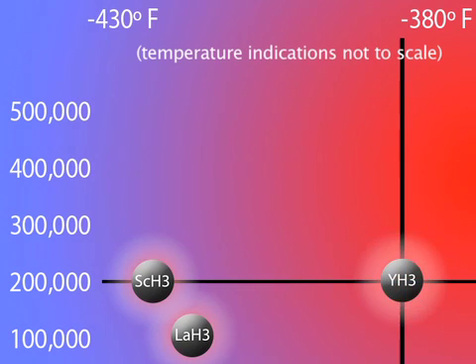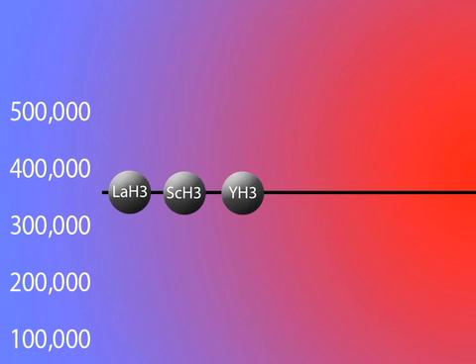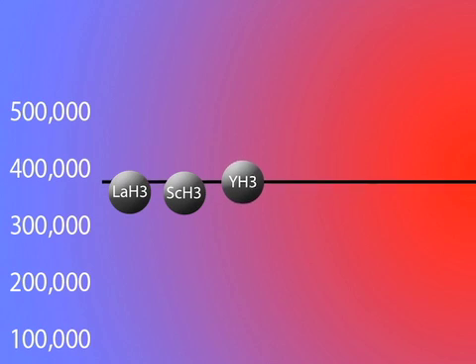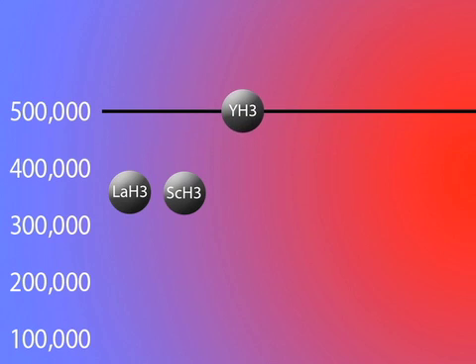At pressures higher than 350,000 atmospheres, superconductivity disappeared and all three compounds became normal metals. Yttrium trihydride became superconducting again at about 500,000 atmospheres, but not the others. The scientists attributed this result to its different mass.